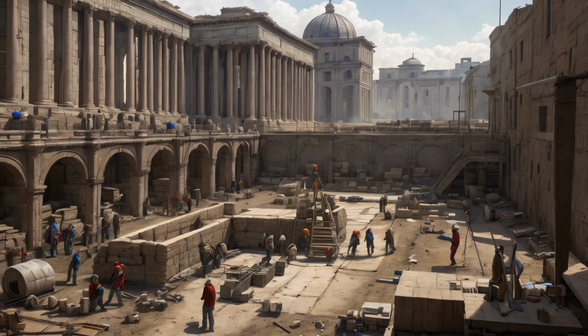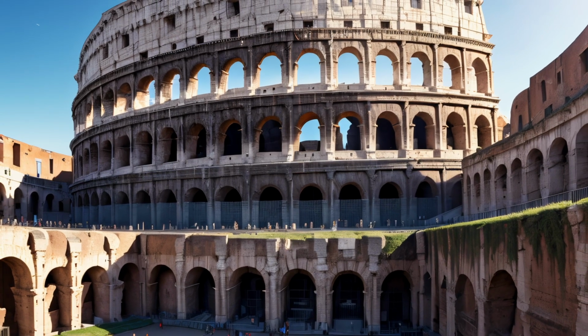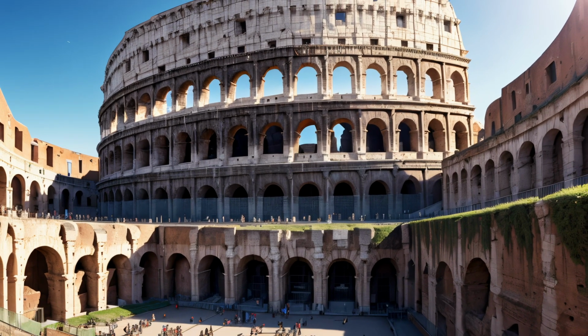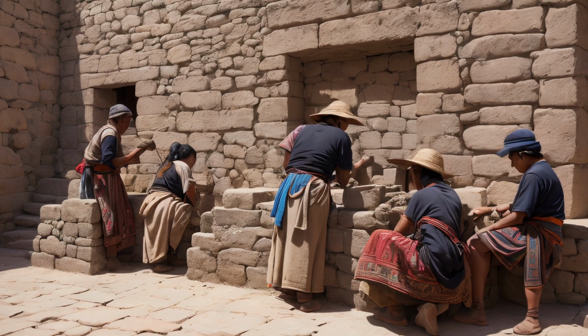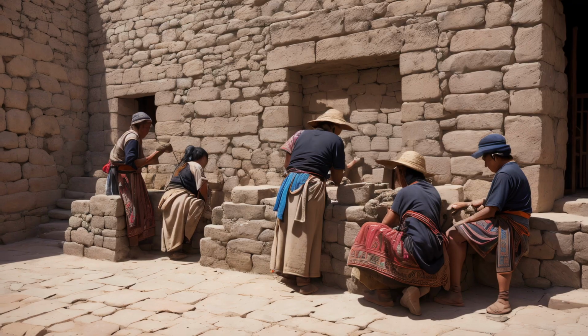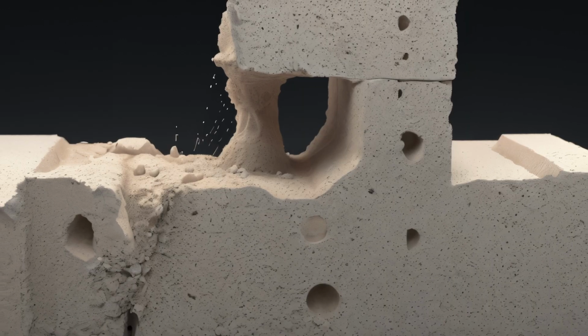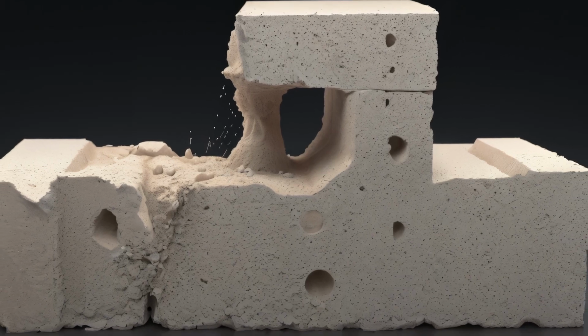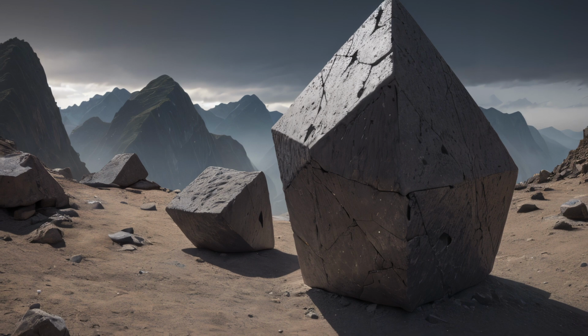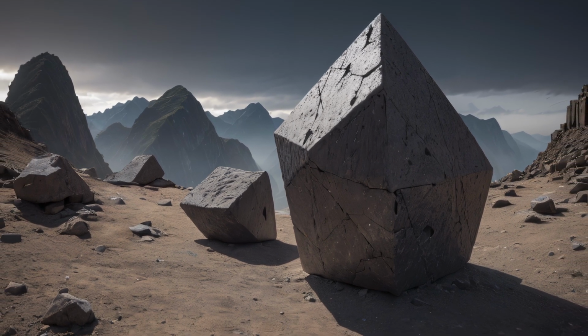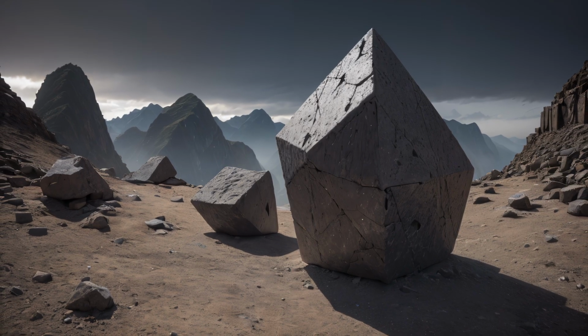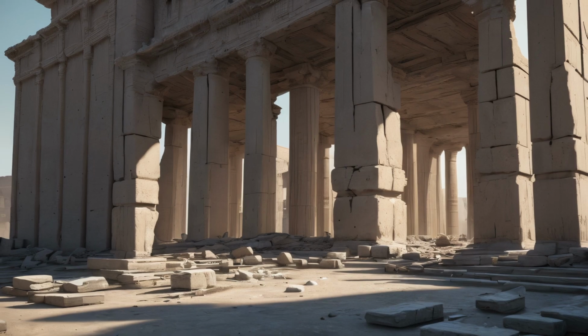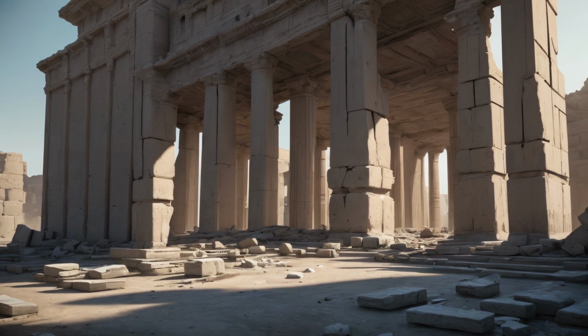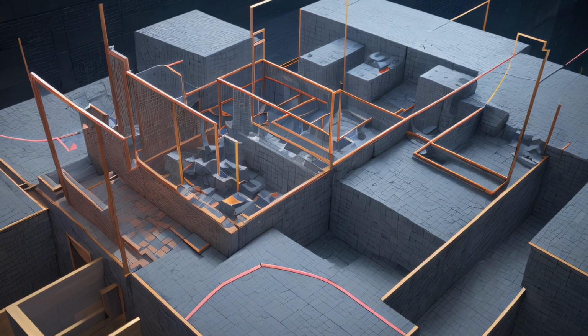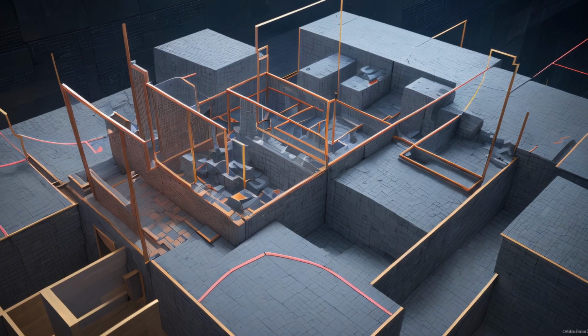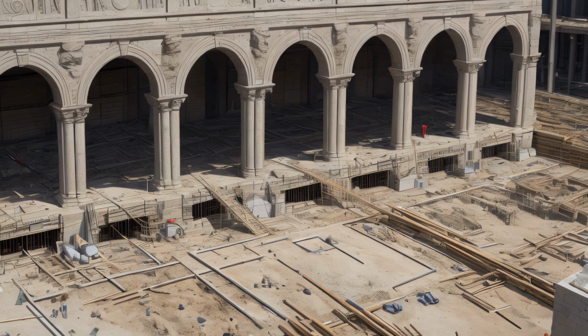Their precisely cut trapezoidal stones, fitted without mortar, formed a system where compressive forces were transferred along joint surfaces via friction and geometric precision. While grouting was absent in most Incan masonry, some coastal structures incorporated lime-based infill materials between massive stone blocks to reinforce critical load-bearing joints, suggesting an adaptive approach to material selection based on environmental conditions. Both civilizations demonstrated an understanding of stress dispersion through distinct methods. The Romans relied on chemical cohesion within a monolithic structure, while the Incas leveraged geometric interlocking to allow controlled movement without displacement. This divergence highlights how technological innovation was not solely dependent on modern materials, but emerged from empirical experimentation